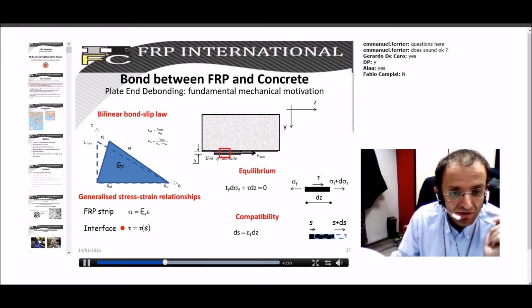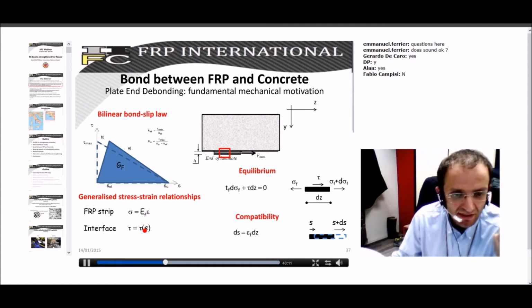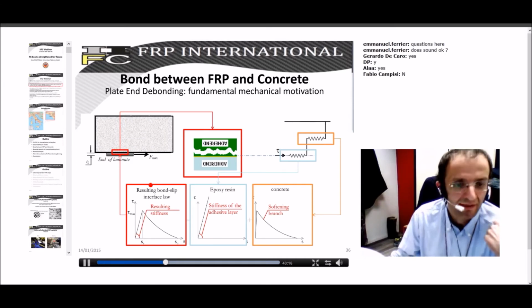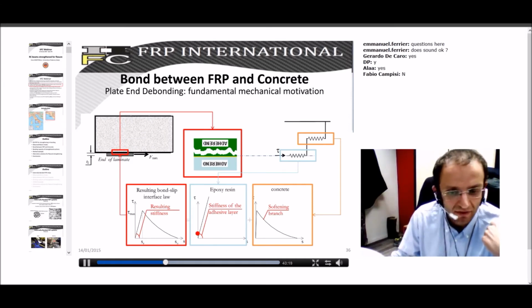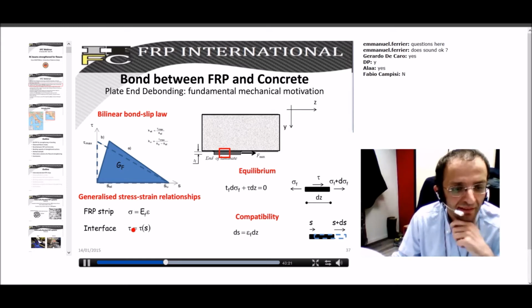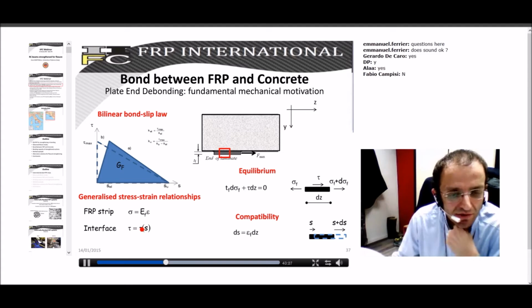What changes is not the stress-strain relationship for the FRP strip, which is indefinitely elastic. The change is just inside the tau slip relationship, which is no longer indefinitely elastic, but is elastic and then softening. In this writing, it is not an explicit equation, but this writing highlights that tau is just a function of slip. It is a general non-linear function of the local slip.